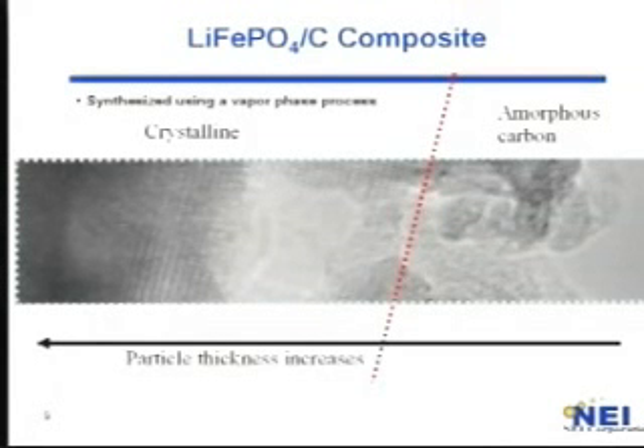This process worked fine. We were able to make a reasonable material and withdraw reasonable electrochemical capacity. However, we ended up adding almost 35% carbon in the lithium iron phosphate. That means effectively we have reduced the capacity utilization of the lithium iron phosphate composite. Because again, there is a lot of limitation of this material if you want to use it for large size batteries. So the goal is: can you reduce the carbon amount, and can you produce the whole material in one single